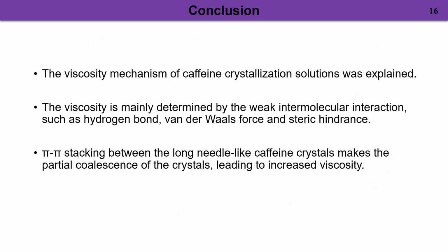So the final part is my conclusion. This paper explains the viscosity mechanism of caffeine crystallization solutions by combining experiments and simulations. The results indicate that the viscosity of caffeine crystallization solutions is mainly determined by weak intermolecular interactions, such as hydrogen bond, van der Waals force, and steric hindrance.